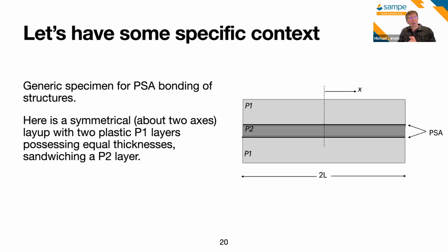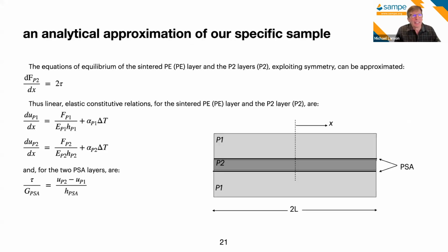So if we put this in a specific context and think about two or three bulk layered materials, and we're going to be adhering these with PSA layers, and I think for PSAs, thinking in terms of plastic materials, the polyethylenes, polypropylenes of the world that are finding more and more applications, is the sort of materials that lots of people are looking to join with PSAs. And that's challenging because those, particularly polyethylene, are notorious for having a very low surface energy of adhesion, and PSAs are showing they can be a good solution. So we have this, and just for giving us some insights, it's symmetrical about the center. This is pretty easy to develop a simplified analytical model to get our head around what's going on.